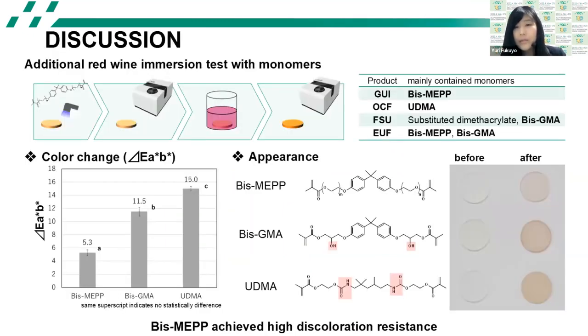In order to verify the reason for the discoloration property differences, an additional immersion test was carried out with monomers, BIS-MEPP, BIS-GMA, and UDMA, by means of the previous test method. And these monomers are mainly contained in each product I show in here. The result of this test is shown on the left side.